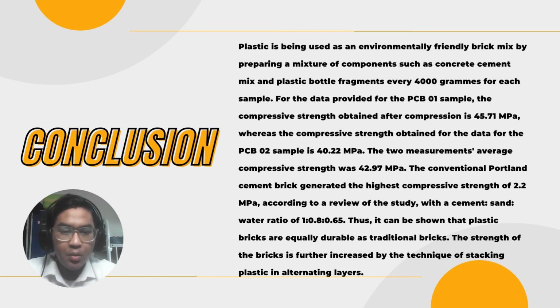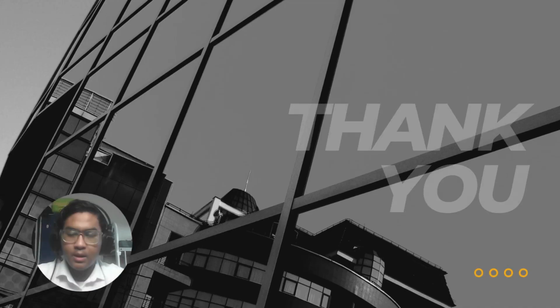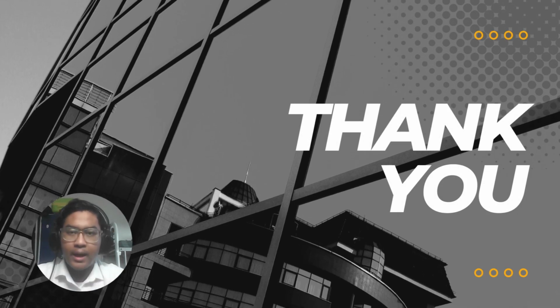The conventional Portland cement brick generates the highest compressive strength of 2.2 megapascal, according to the review of the study, with a cement: sand: water ratio of 1:0.8:0.65. Thus, it can be shown that plastic bricks are equally durable as traditional bricks. The strength of bricks is further increased by the technique of stacking plastic in alternative layers, which is achieved in our project. All right, I think that's all from us, Group KA05.